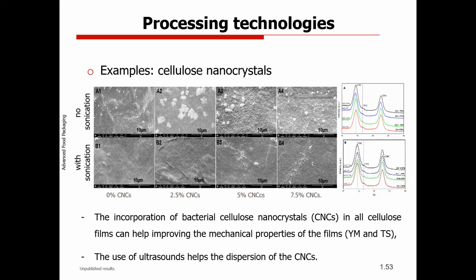The idea was to reinforce these materials, trying to improve the mechanical and barrier properties of these films. What we can see here, with no sonication and with sonication, is that when you are producing these solutions and mixing everything together, if you don't apply a sonication process, ultrasound processing, you are not able to disperse these nanocrystals. And when you are not dispersing these nanocrystals, the addition of these additives is not giving you any kind of advantages.